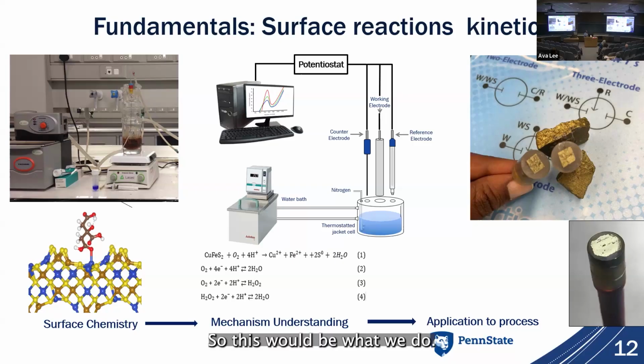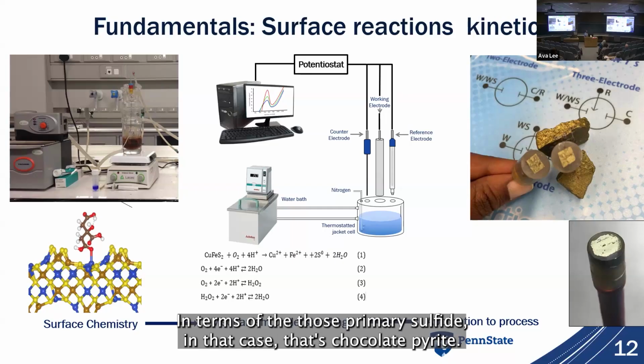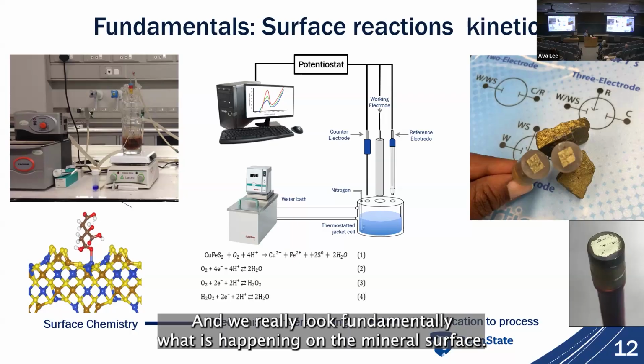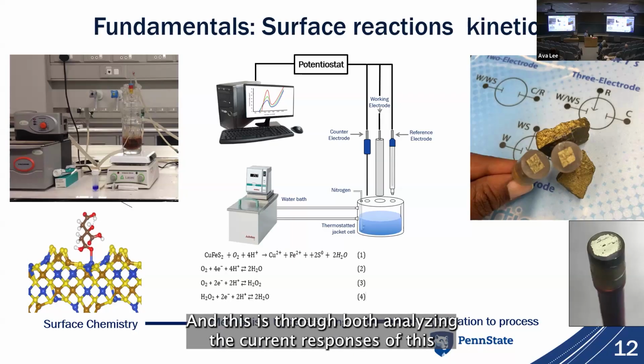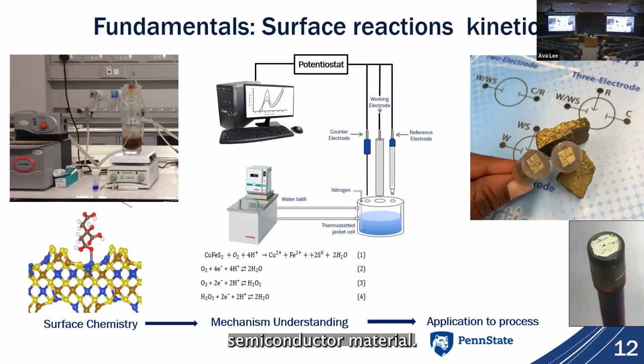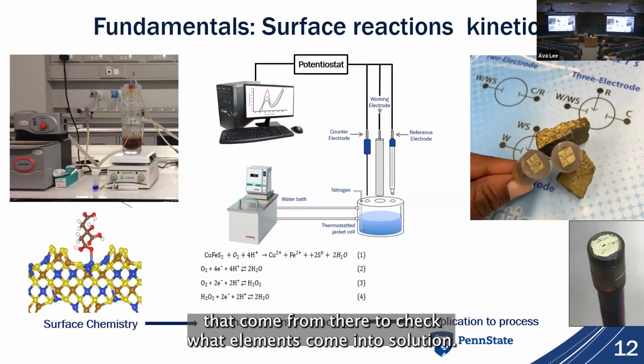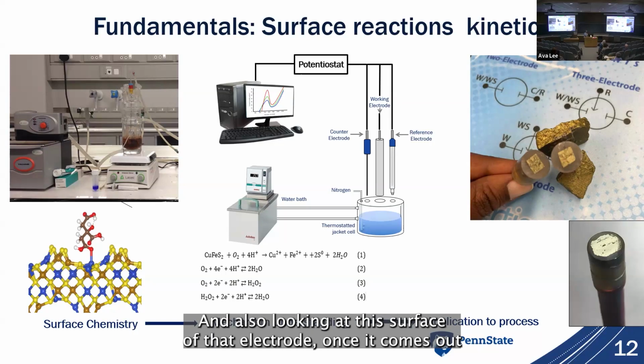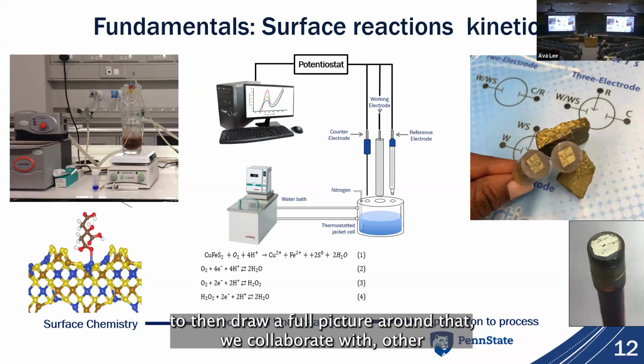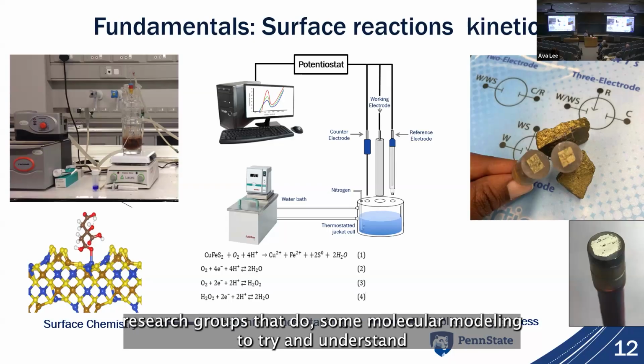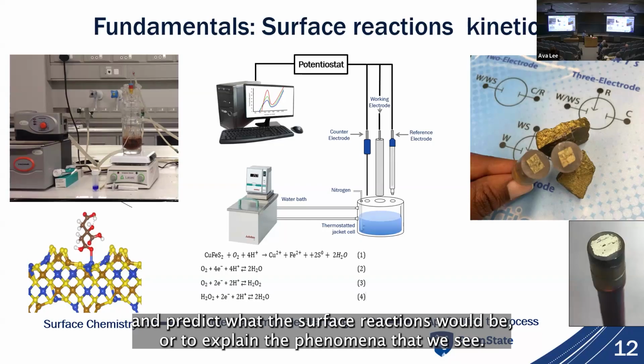So this would be what we do. We take our minerals, we make them into electrodes in terms of this primary sulfide. In that case, that's chalcopyrite, and we really look fundamentally at what is happening on the mineral surface. This is through analyzing the current responses of this semiconductor material, and also looking at the solutions that come from there to track what elements come into solution, and also looking at the surface of that electrode once it comes out to then draw a full picture around that. We collaborate with other research groups that do some molecular modeling to try and understand and predict what the surface reactions would be, or to explain the phenomena that we see.